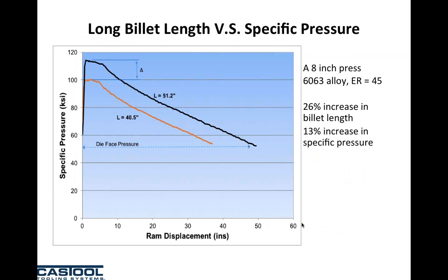A lot of presses have gone to longer billet these days. With longer billet, we've increased the amount of friction lost between the billet and the container. And typically about 30% of our total press pressure is lost to friction between the billet and the container. If we increase the billet length by 10 inches or 20 inches, we need more pressure to be able to break through the die. What would happen if we went from a 40 to a 60-inch billet and we had adequate pressure for a 40-inch billet is that at 50 or 60 inches, more of that pressure would go to friction and we wouldn't be able to break through the die. So we actually have to increase the tonnage capabilities of the press.